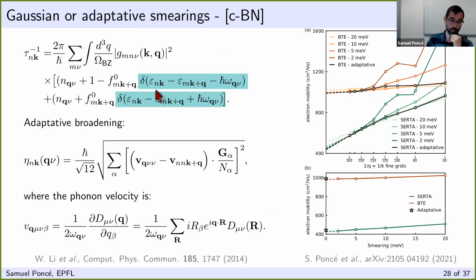So something I should mention here, which is a bit technical, is the fact that in all of those equations, you have those Dirac deltas, in the scattering rate, but also in the Boltzmann transport equation. And those Dirac deltas can be described by a Gaussian or a Lorentzian. And so in EPW, you can describe them with the degauss input variable with a finite value. And you can also use adaptive broadening. This was introduced in this paper. What it means is that you're going to use a Gaussian with a width which is equal to this formula. And so this means that you will have a different Gaussian width for each k-point, q-point and band.